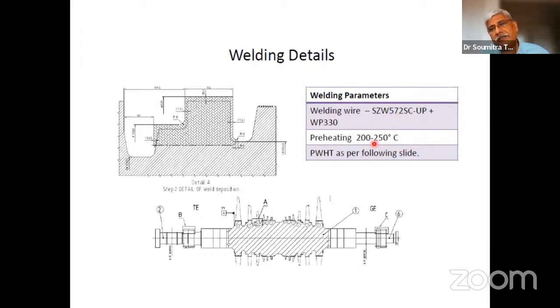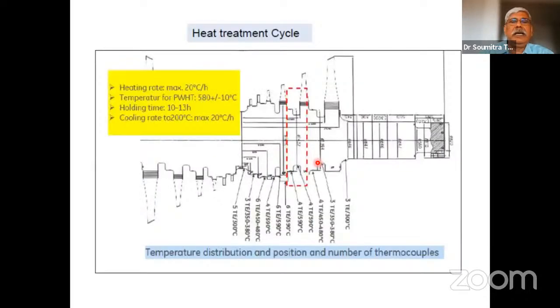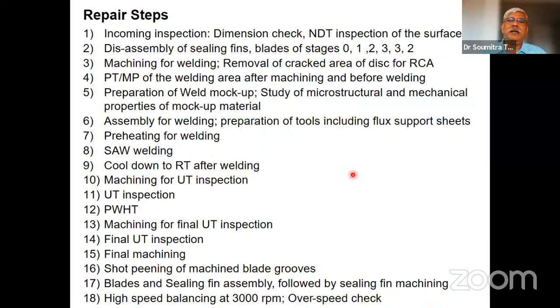It had to be preheated, and think of such a big component which had to be preheated, and then post-weld heat treated afterwards. And during post-weld heat treatment, these are the parameters. It had to be post-weld heat treated to 580 degrees centigrade, but making sure that the temperature of nearby regions doesn't go much beyond 400 or even 300. So there had to be a lot of insulation, a lot of local heating, and a lot of monitoring of the temperature profiles using thermocouples while the post-weld heat treatment was going on. And there had to be a lot of non-destructive evaluation, testing and evaluation to make sure no defects are generated.